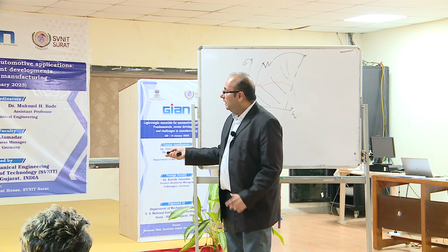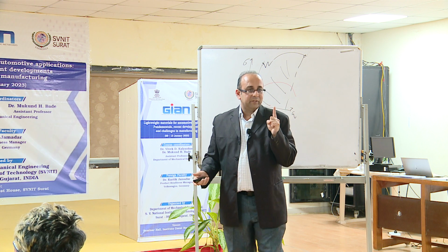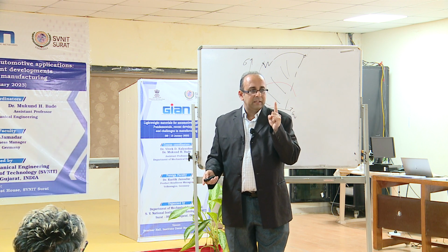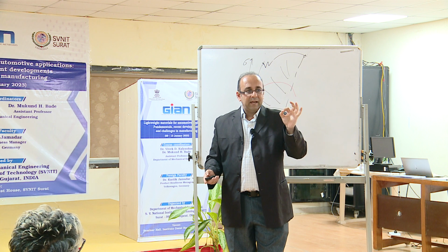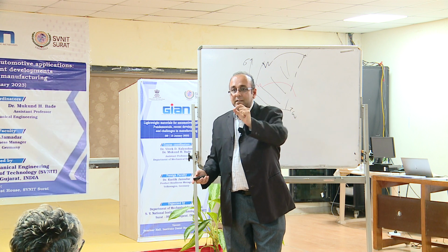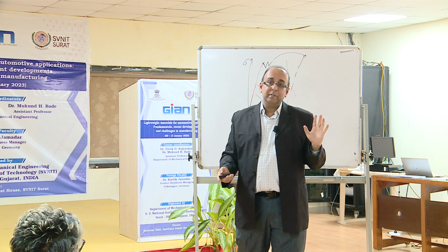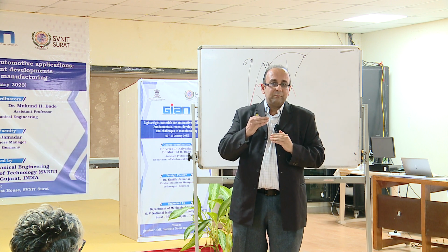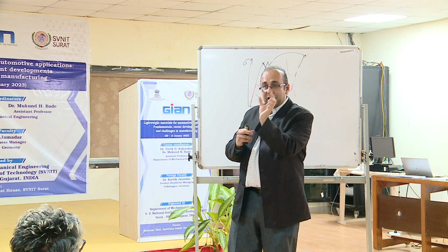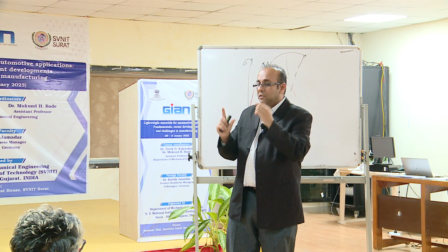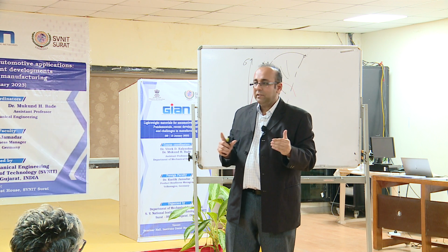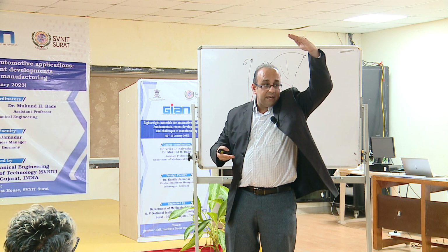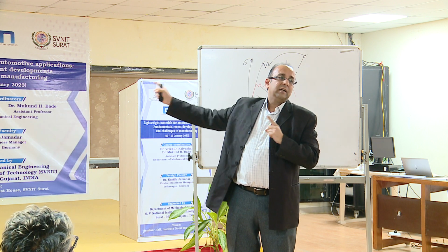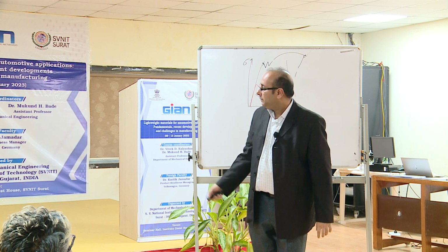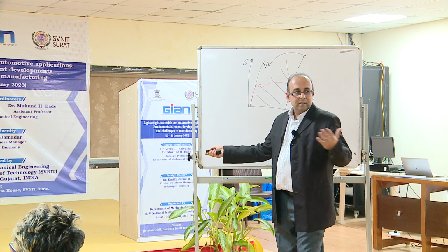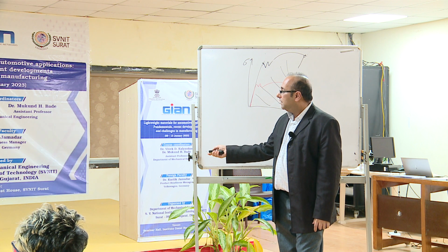Dual phase steel, here now the temperature started coming into the picture. Why did temperature start coming into the picture? Because your retained austenite is converted to martensite, but even the ferrite is kept in the picture. So we are controlling the temperature such that you produce ferrite as well as martensite. So first time the temperature came into the picture, obviously temperature in terms of austenite, and then going back down in terms of DP material, dual phase material. Then came the complex phase material and finally the martensitic steel.